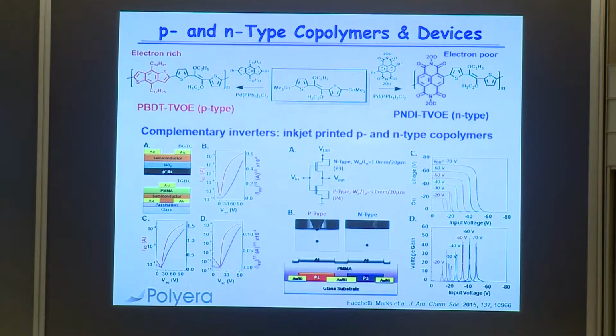And we characterize these in all the ways that one characterizes the structure and molecular weight distribution of a polymer. And this is N-type because of this very powerful electron acceptor. If I do similar chemistry but add this electron-rich building block here, both of these are copolymers, I make a material that's p-type. And both of these have roughly the mobility of amorphous silicon. They're soluble. You put on organic groups that make them soluble.